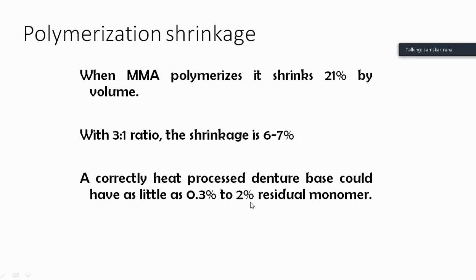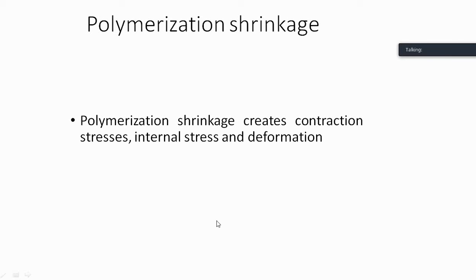A correctly heat processed denture base could have as little as 0.3% to 2% of residual monomer. Residual monomer means the amount of methyl methacrylate which is unreacted, and this is also an unwanted byproduct which we do not want. So if our processing, proportioning, everything is correct, the residual monomer can reach up to 0.3 to 2% only. Polymerization shrinkage creates contraction stresses, internal stresses, and deformation. These are the side effects of polymerization shrinkage.